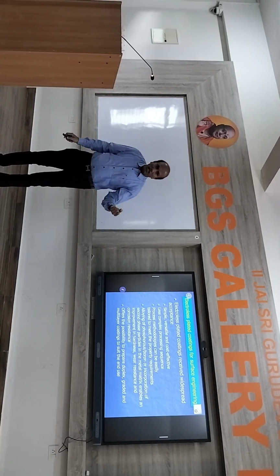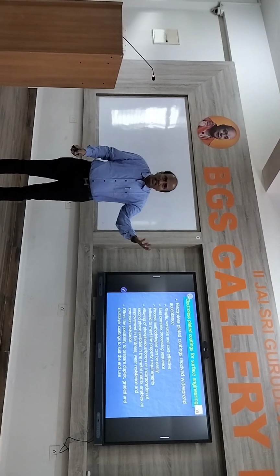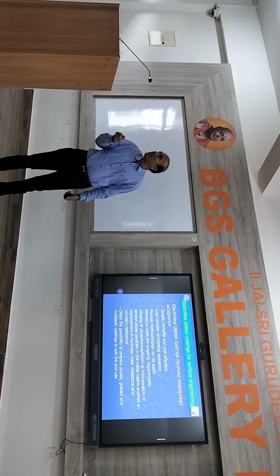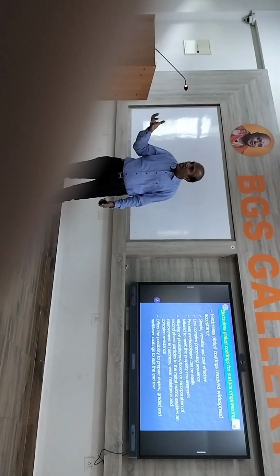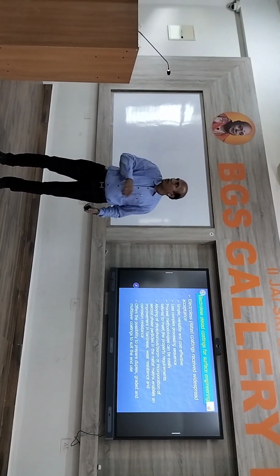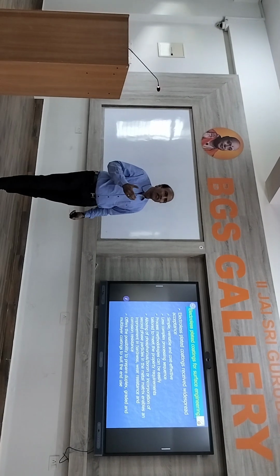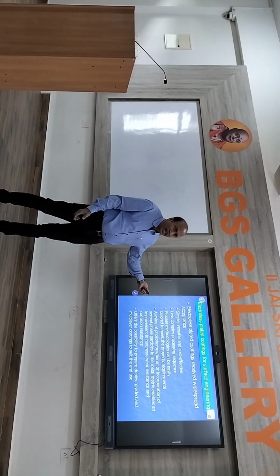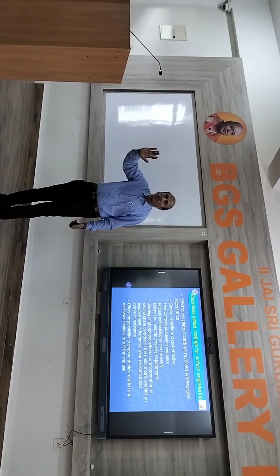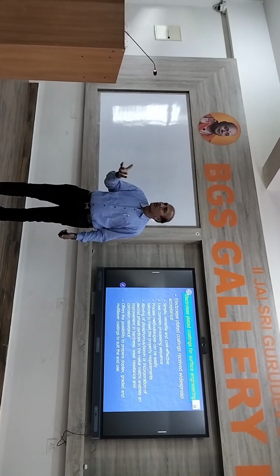For example, I want to have a very hard coating. I will always prefer electroless coating with silicon carbide particles, tungsten carbide particles, or you can choose molybdenum disulfide, like lubricant particles, or hexagonal boron nitride particles. A variety of these particles can be co-deposited and used for various applications. For example, I want a coating which gives very good corrosion resistance. I can tailor it in such a way that my coating will have good passivity. A passive layer should form so that it gives the required corrosion protection. According to my requirement, I can tailor.